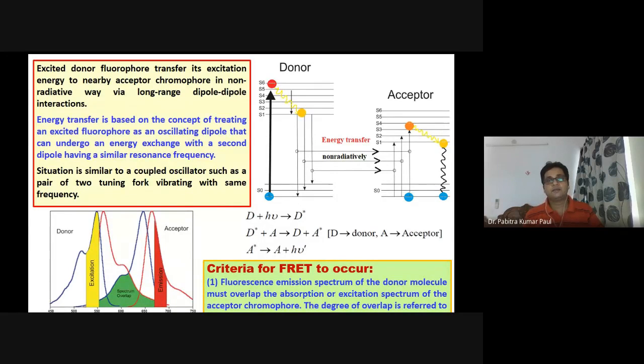One thing is very important, I forgot to mention: the excitation of the acceptor molecule and the excitation of the donor molecule should be far apart. The excitation of the acceptor should be away from the excitation of the donor molecule, so that when we excite the donor molecules, we can avoid the direct excitation of the acceptor molecule. That is, choosing the two molecules is very important. We need to keep in mind the excitation wavelength for both the acceptor and the donor. So that is very crucial.